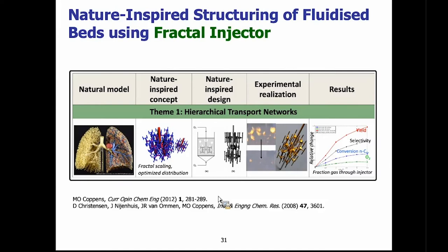And when we came with this idea, at that moment, industrial partners might think this is too complicated to implement. But what can we do now? We can use 3D printing methods. We can use laser sintering methods. We can use additive manufacturing methods to very quickly generate these structures. So as computationally assisted design, understanding of multiphase flow, and materials manufacturing methods have evolved, we can move closer to real applications. So what I show you in the experimental realization can lead to results which you see on the right there. That is, if you have more gas going through the injector in a catalytic process, in this case a selective oxidation process, you can make more of the product you want to make and less of the oxidation to, say, CO2, which you don't want to make.